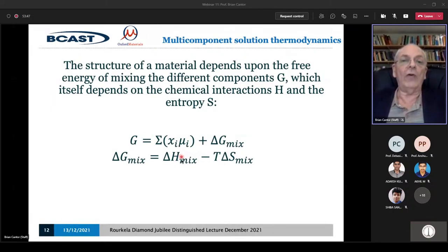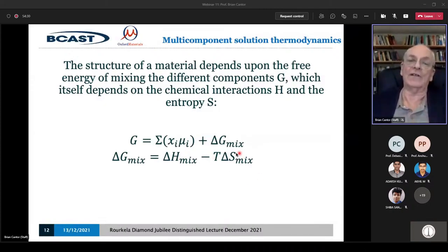But because they're only binary and ternary systems we've ever used, if you start trying to add more, it becomes difficult because the compounds get to dominate, and the materials become difficult to make because they fracture too easily, and you can't form them anyway in the first place. But if you add lots of components, the entropy, which is negative and therefore opposes the energy, gets bigger and bigger and bigger. It opposes the formation of compounds, and what happens instead is the atoms and the molecules mix on the crystal structure rather than forming compounds. So that's why the Cantor alloy formed.